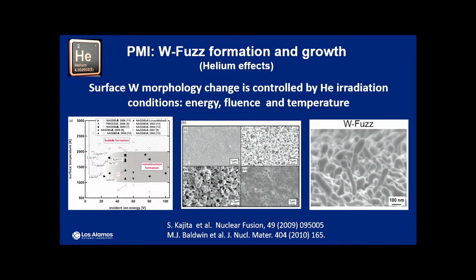All right, another thing. Obviously, the DT products are helium and the neutron. The neutron generates energy. The helium is used for self-heating the plasma. But in the end, those helium ions will get to the wall, the first wall. Studies have shown that depending on the energy of the helium, the temperature of the wall, and the accumulation of the helium fluence, you are going to generate a very strange microstructure on the surface of the beautiful tungsten you start with. Some of those actually look like a fuzz growing on the surface of your tungsten. You can imagine if those things break off and go back to the core plasma, they are going to cause instability of the plasma because they are so heavy and absorb a lot of energy from the plasma. So that is a bigger concern.